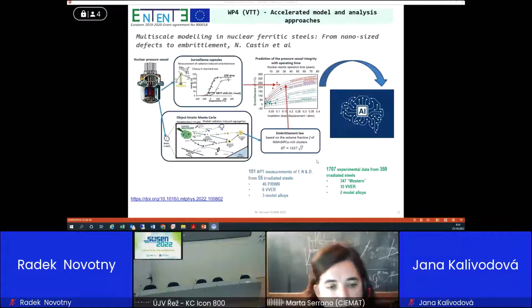I want to show you a very nice example on the exploitation of data with artificial intelligence algorithms. The one is the work performed by Nicolas Castin et al. when they demonstrate that a hybrid model, a hybrid of a kinetic Monte Carlo model, this is a pure atomistic model, coupled with artificial intelligence algorithms, can predict with quite high accuracy the embrittlement of the reactor pressure vessel, only knowing the chemical composition of the material and the irradiation condition. This is already published, and we use 100 atom probe tomography measurements and more than 1,000 experimental data. This is very, very innovative.